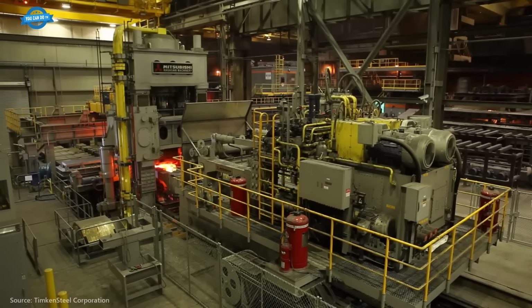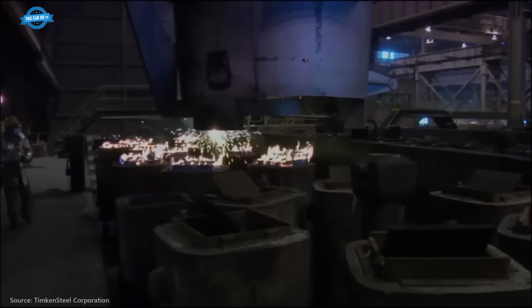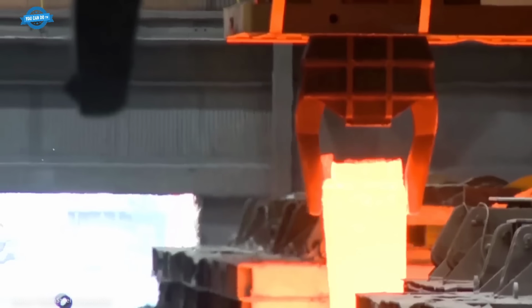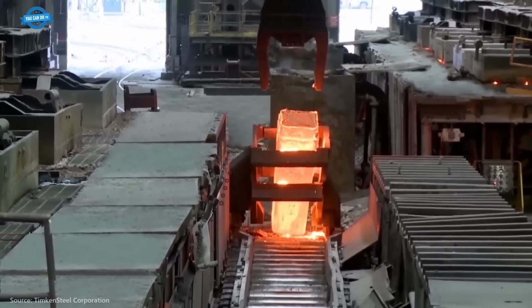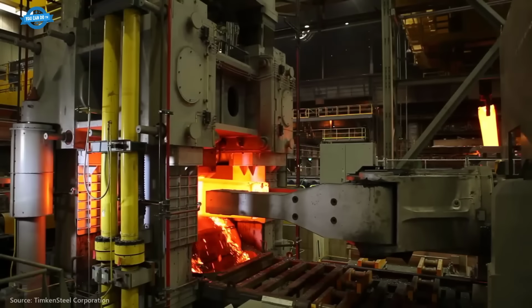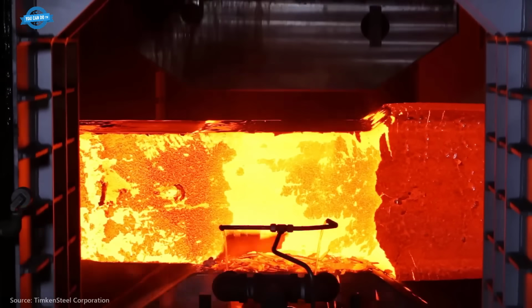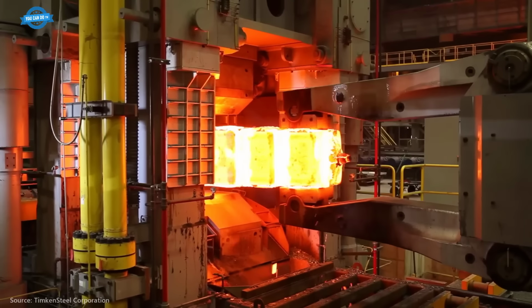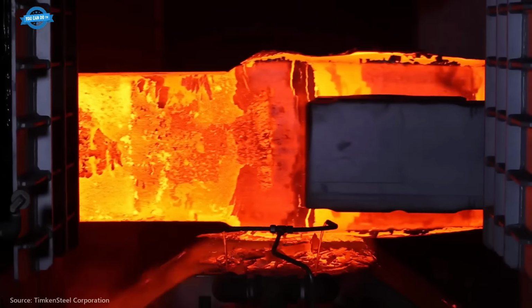The large bar forged rolled process is an advanced metallurgical technique designed to enhance the internal soundness, strength, and uniformity of special bar quality (SBQ) steel. This process begins with an as-cast ingot, which is first reheated in a soaking pit to achieve a consistent temperature. The ingot then undergoes multiple forging passes in a 3,300-ton forge press, applying uniform pressure along its entire length. This precision forging significantly improves the ingot's internal structure, reducing center porosity and enhancing overall mechanical properties.